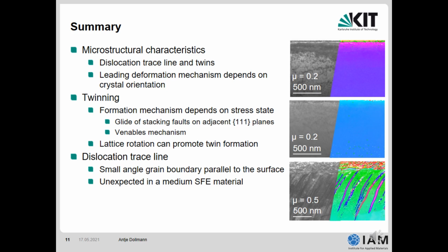Concerning the dislocation trace line, we have seen that this can also be formed in a material with a medium stacking fault energy, and it has the small angle grain boundary characteristic parallel to the surface, as we have seen before in copper and its alloys.